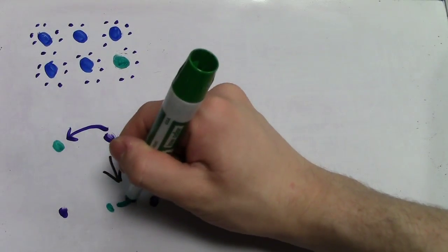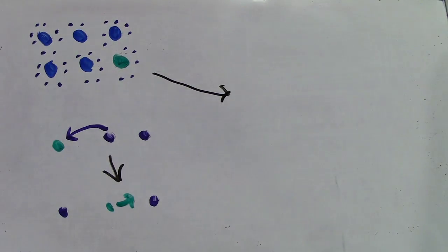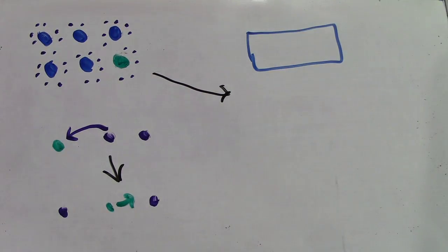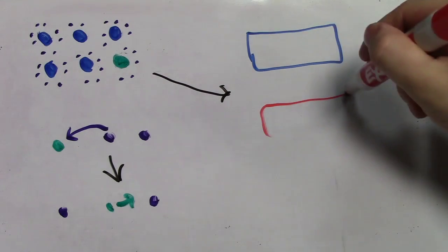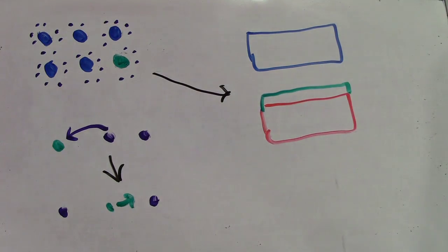The hole will move when other electrons move to fill the hole's spot, but just ends up creating a new hole. So in this sense, the hole can be seen to travel through the semiconductor in the opposite way of an electron. This also decreases the size of the band gap by adding an energy level right above the valence band for electrons to flow into. This type of doping creates a P-type semiconductor.